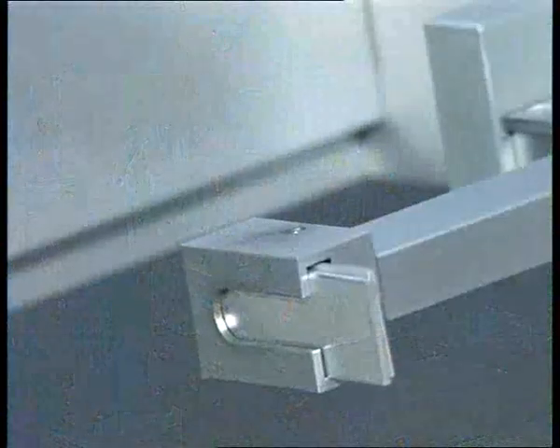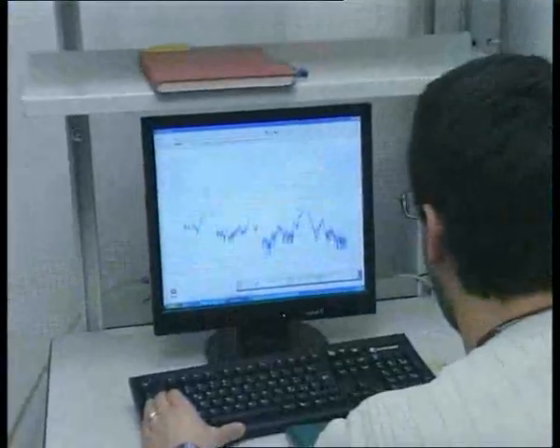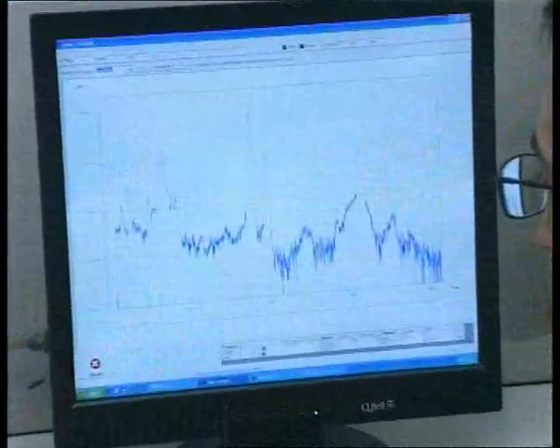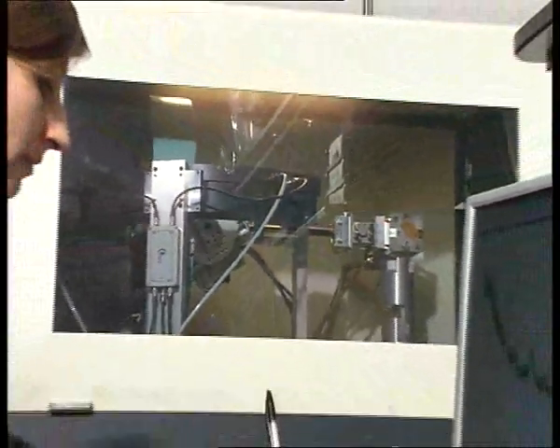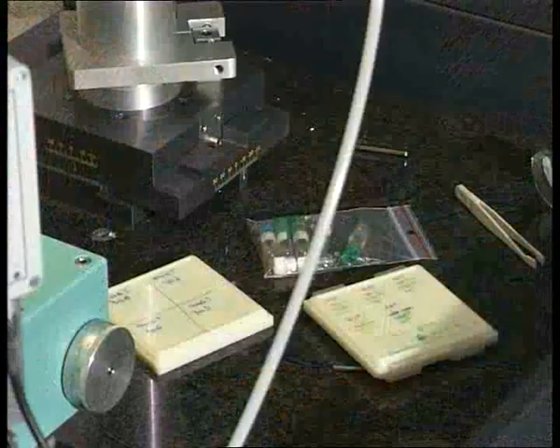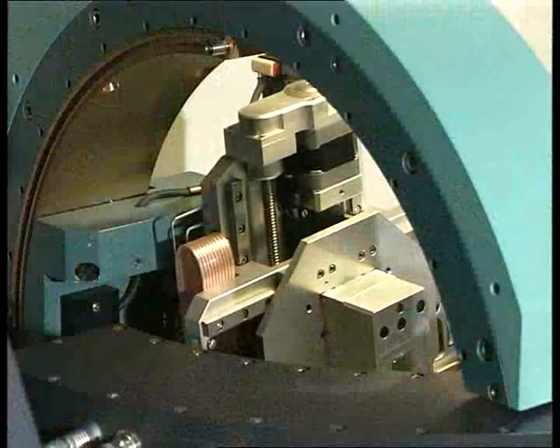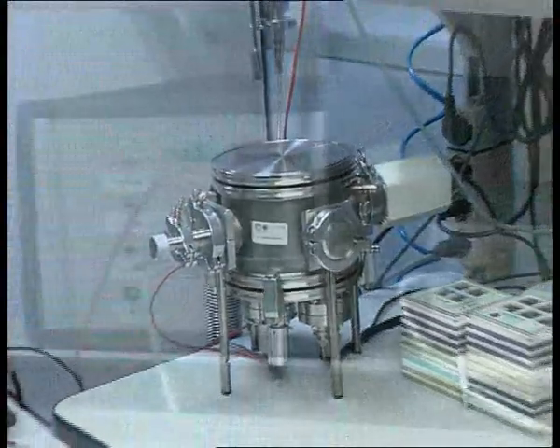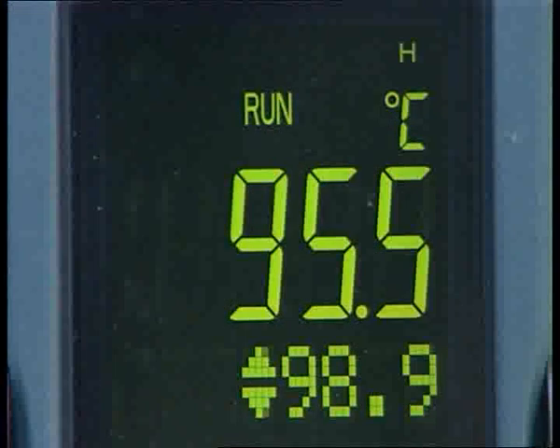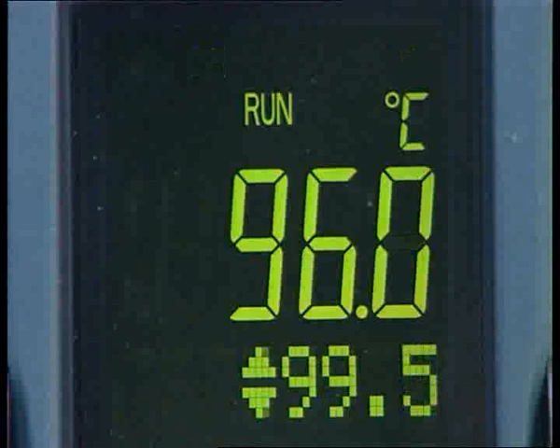The chemical composition of the deposited chalcogenide materials was measured by total reflection X-ray fluorescence analysis in a system especially designed for this purpose. In germanium antimony telluride, generally called GST, the chemical ratio was precisely evaluated. The crystallographic structure was probed by X-ray diffraction in grazing incidence geometry. The phase transition from amorphous to crystalline, corresponding to a 0-1 of a memory cell, was followed by resistivity measurements as a function of temperature using the van der Pauw configuration.